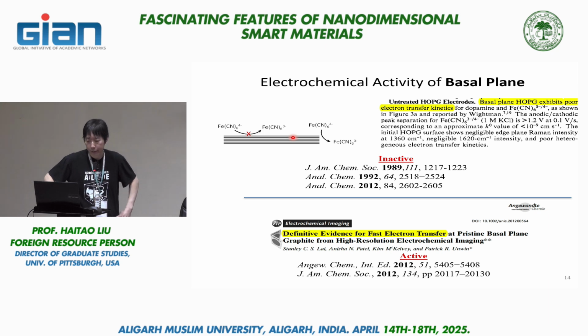It makes sense. Okay. Except in early 2010, a group in the UK, Professor Patrick Unwin, a very well-known electrochemist doing a lot of interesting work in scanning electrochemical microscopy, published a series of papers, and if you look at the title, "Definitive Evidence of Fast Electron Transfer at Pristine Basal Plane." His study showed exactly the opposite conclusion from the early conclusions made by McCreery's lab. McCreery said the electron transfer at the basal plane is poor, and Unwin said it's fast. And they're both very well-known and very respected electrochemists in the community.